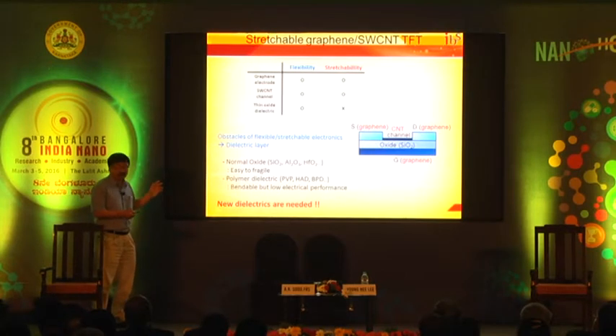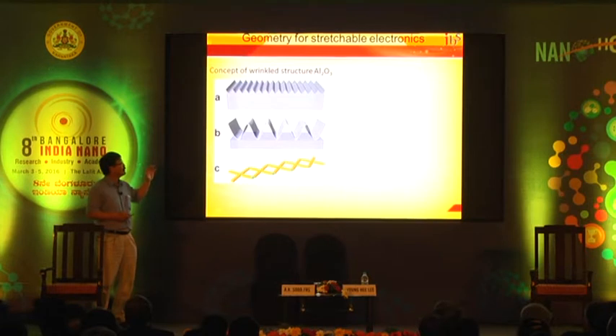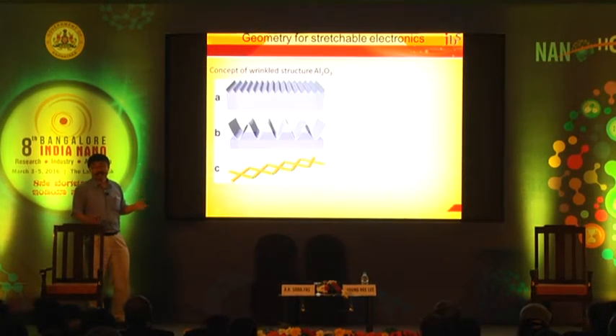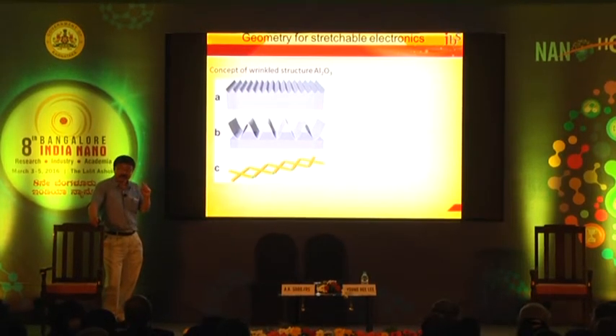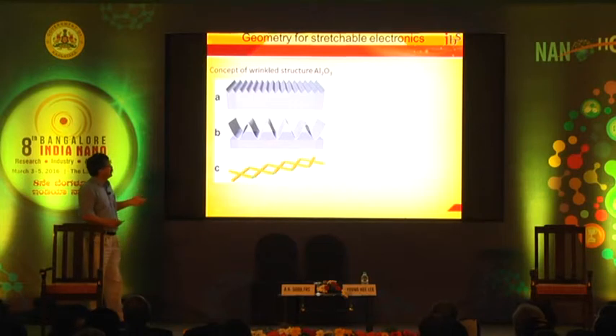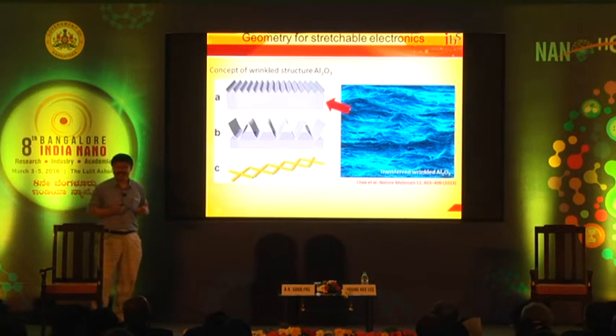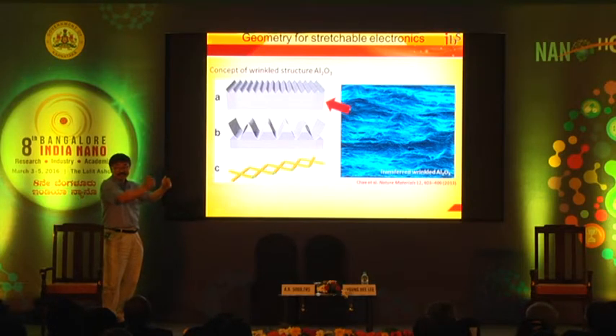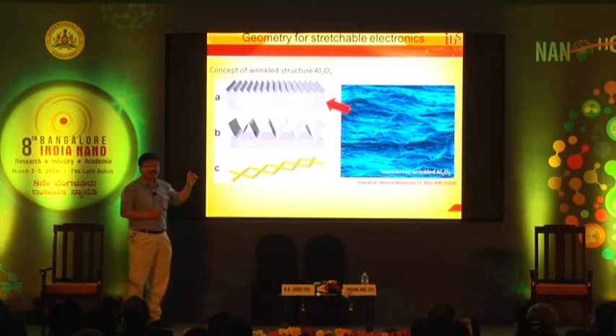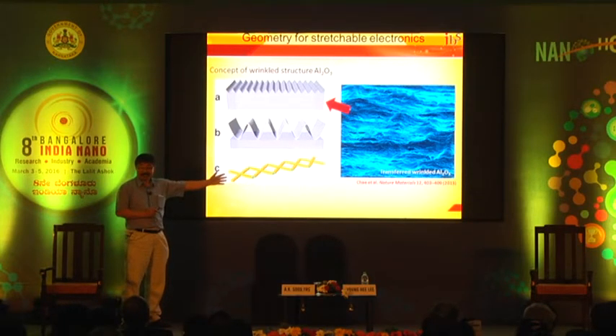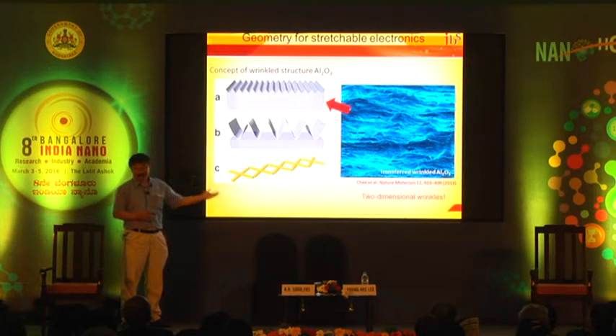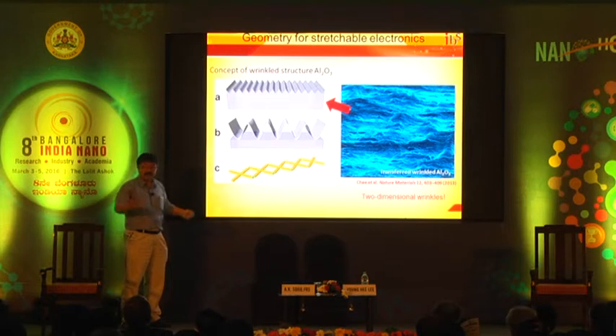Then we thought about what we can do, and we wondered, can we really use an inorganic oxide? Nowadays we can have thickness control of aluminum oxide or silicon oxide using the ALD method, atomic layer deposition, but still they are inorganic. But if you make some kind of wrinkle structure, like cotton, even though you move it back and forth, nothing happens actually. So if you implement this wrinkle structure in the oxide, it should be okay. So we actually created two-dimensional aluminum oxide wrinkles, and then they can be stretchable.